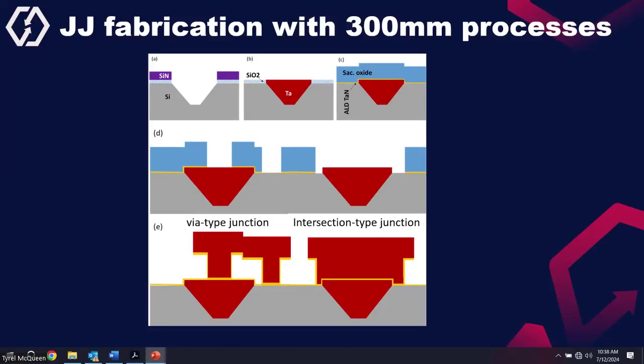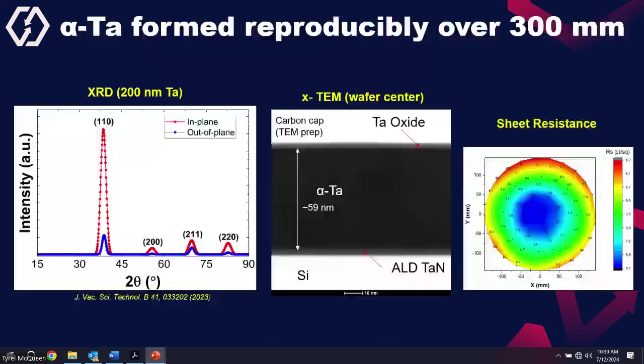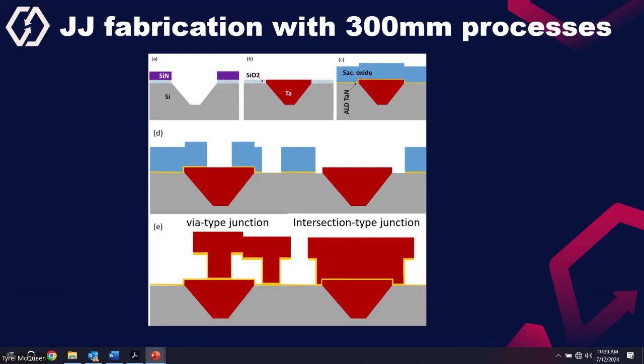So after the bottom electrode is established, we deposit a sacrificial oxide, which is basically silicon dioxide. And using 193 nanometer lithography and reactive ion etching, we create this trench. And then we deposit our tunnel barrier and the top electrode. Here is how the Josephson junction looks. This is the bottom electrode, then the tunnel barrier, and then the top electrode. Yes, we have ALD tantalum nitride in our tunnel barrier.